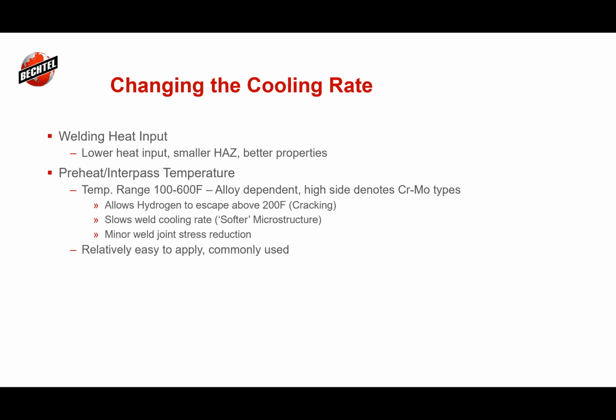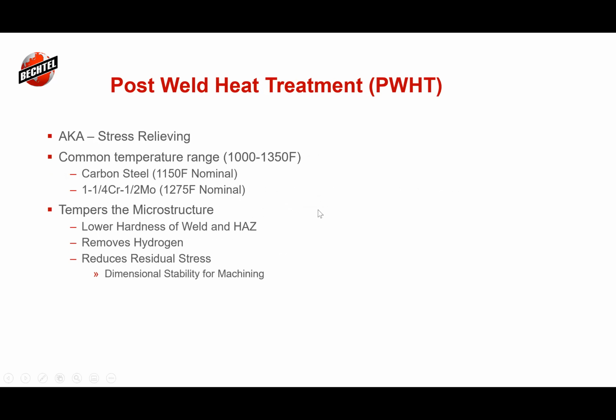I put in there the 100 to 600 because it was from a different presentation. Typically 600 is only something you'd see on the P91 type alloys, the 9% chrome 1 moly vanadium. But there's a balance. Having a preheat of around 200 does allow hydrogen to escape, and can improve your inner pass hydrogen diffusion as it comes out. Some of these are pretty easy.